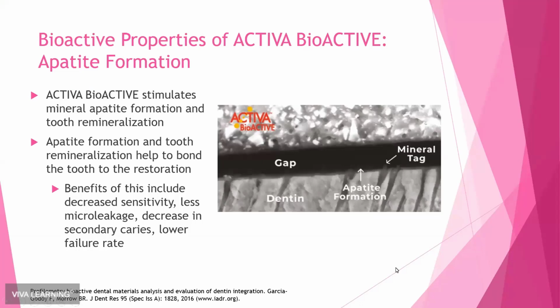This is a really cool graphic, and I hope this is clear for everyone to see. So this shows the mineral tags, or the apatite formation, that is happening between Activa Bioactive, which is the top part of this image, and then the dentin of the tooth, which is the bottom part of the image. The apatite formation that happens between the tooth and the restoration helps to really create a tight bond between the material and the tooth. It helps to decrease sensitivity by sealing those dentinal tubules. It helps to decrease microleakage at the margin, and like I said, to prevent secondary caries because you have this strong bond. And I just think it's really neat to actually see this versus just knowing that it's true.